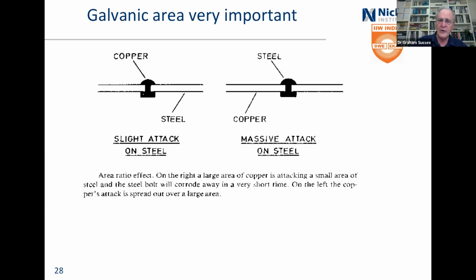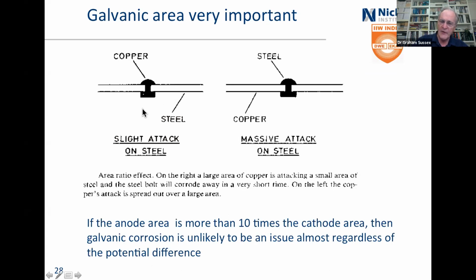And the galvanic area is very important. This is back to looking at Davy with his putting copper onto boats to get rid of woodworm. Yeah, wooden boats. And he found that the steel corroded very rapidly, and that was a problem. So then he started using it the other way around, and it worked quite well, except that he didn't have enough copper there. If the area of the anode is more than about 10 times the cathode area, galvanic corrosion is not all that likely, and it really doesn't matter all that much what the potential difference is. That's not completely unlikely, but at reasonable levels of difference, the 10 times is pretty good. If it's the other way around, with the anode 1/10 of the area of the cathode, then you're likely to be in trouble at really quite low potential differences.